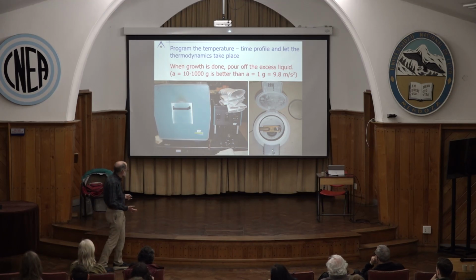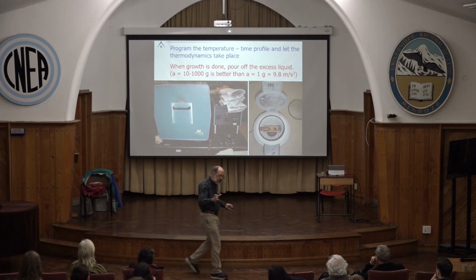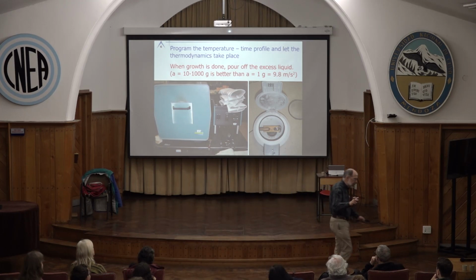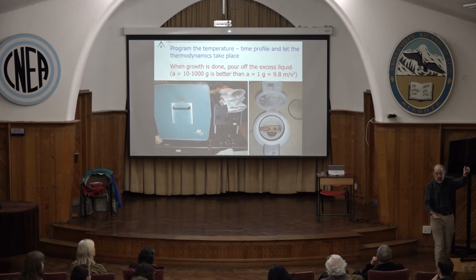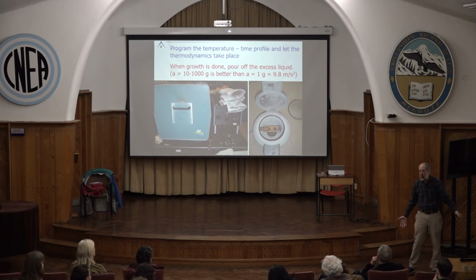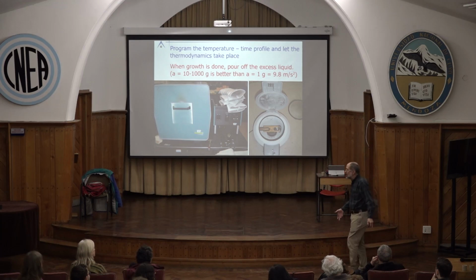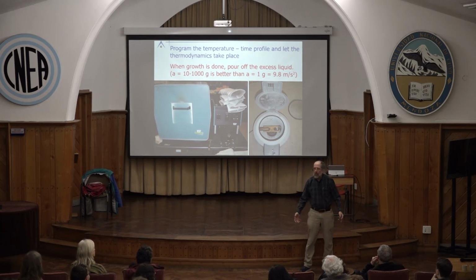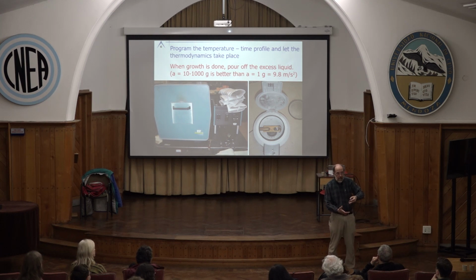If you grew salt or sugar crystals out of water, you can pull it out of the water. If you grow salt or sugar crystals out of water and cool the water down to minus 100 Celsius, then your sugar crystal's stuck in ice, and you would say that's sort of a stupid thing to do. Well, the problem here is I'm growing this out of antimony. Antimony solidifies at about 600. I can't pull it out, so I have to pour off the antimony.